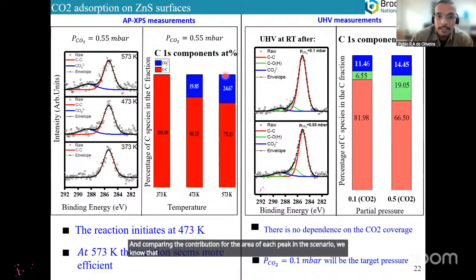Usually from the literature, this peak is assigned to the CO2 fingerprint. So this result might indicate that the reaction initiates at 473K, and comparing the contribution from the area of each peak, we know that at 573K the component related to the CO2 species is most likely higher than at 473K. So at 573K, you can say the reaction seems more efficient.